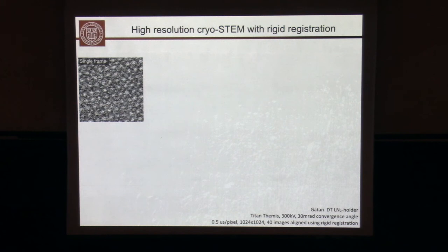The reason why it's difficult is this: when you cool a system in the microscope, the space you have is very small. That means efficient cooling is difficult, and you often suffer from very strong drifts and instabilities of the stage. We have figured out a way of compensating for that, and we do it in image processing. It's a combination of an acquisition scheme that involves very rapid acquisition, so that the signal to noise ends up being very low.